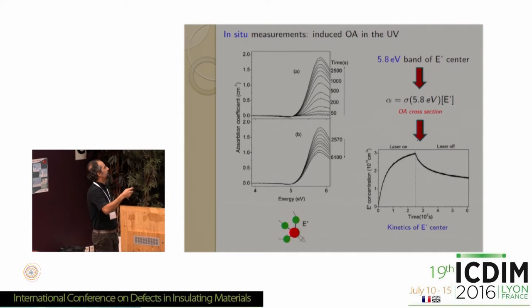Since the absorption cross-section of this defect was known, one can translate this data into concentration data. So, eventually, from this data, we get the kinetics of the concentration of the defect as a function of time. As I told you before, there is this growth and then a spontaneous decay in the post-irradiation stage. Of course, if this same experiment had been done with an ex situ approach, we would be only able to see the overall combined effect of growth and decay.